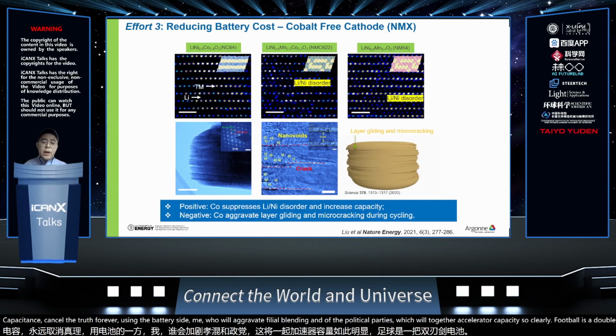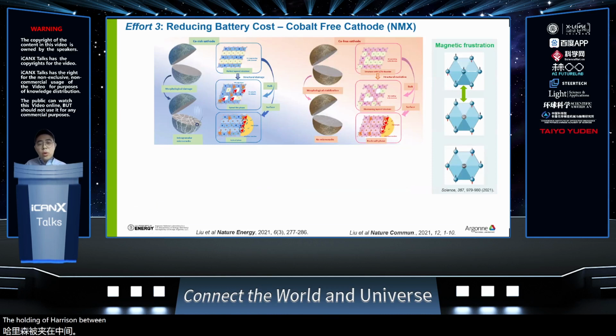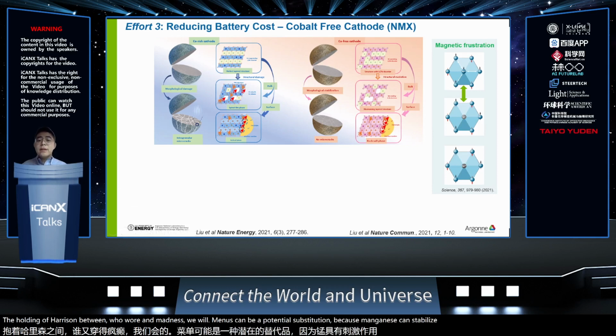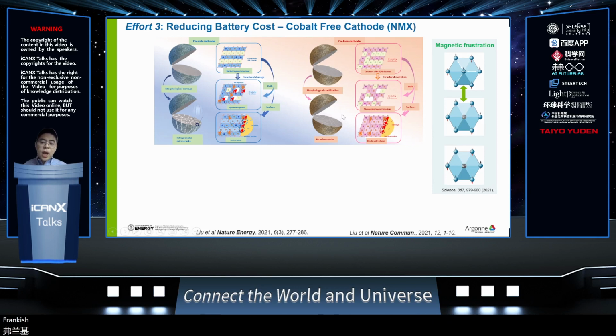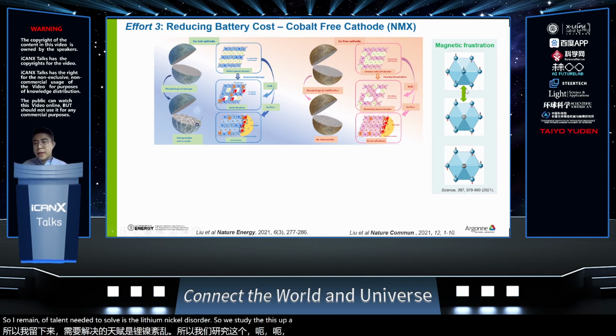The following comparison between cobalt and manganese reveals manganese can be a potential substitution for cobalt, because manganese can stabilize the structure and also suppress the particle cracking. So a remaining challenge to solve is the lithium-nickel disorder. We studied this problem in a separate work.